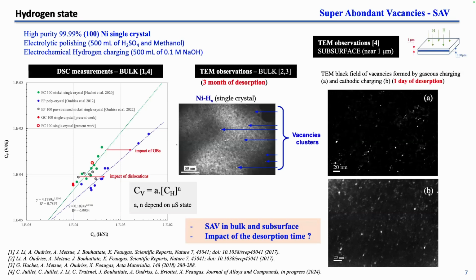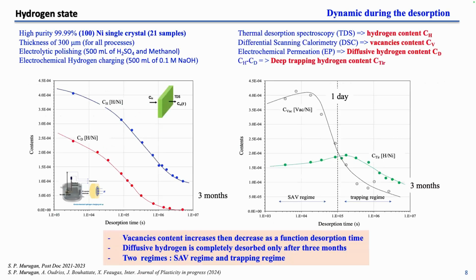This production of vacancies by hydrogen in the bulk has been checked with TDS three months ago here, but it has also been observed in the subsurface, at a distance of 1 micrometer, when you compare gaseous charging and cathodic charging. We show that for the same thermodynamic condition, when we shift from the overtension to the fugacity, we do not have the same density of vacancies. These are interesting results for the future.